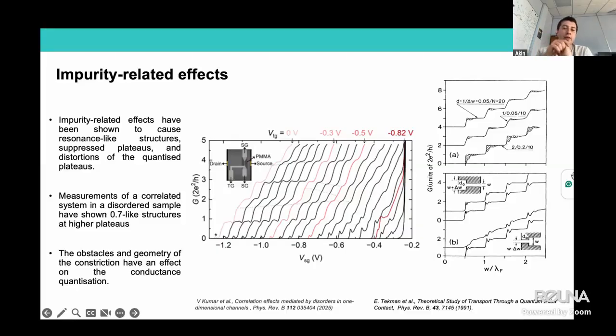Another anomalous behavior can be created in the system due to impurity-related effects as well. This is a theoretical study from Tekman, 1991, where they analyzed what impurities or different conductance shapes can create deviations from quantized conductance. You can see some certain plateau-like structures or resonances. And this is an experimental study from Vivek, a postdoctoral researcher in my group, where they have seen correlation effects mediated by disorder in these systems. I think an interesting result that they have observed is 0.7-like features in the higher plateaus as well.